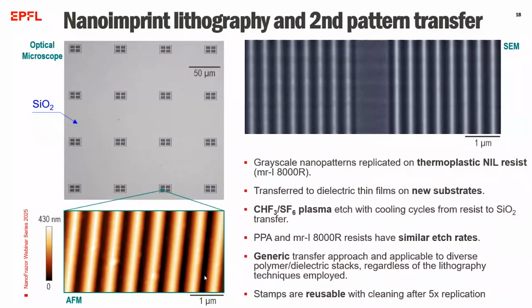Here you see images of fabricated sinusoidal surfaces after replication with nano-imprint lithography on thermoplastic resist and second pattern transfer into SiO2. But as I told you, it's another substrate. Generally, it's on a wafer. In this case, the sine shapes have relatively higher depths, around 400 nanometer and 500 nanometer pitch. So it means that we have an aspect ratio of approximately 1, and we can achieve relatively higher depths with the amplification process during the plasma.